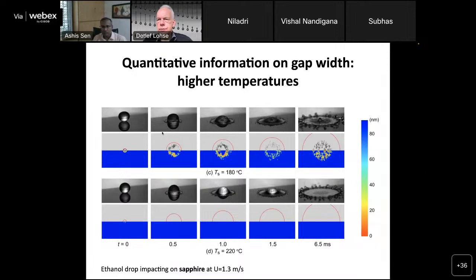More questions? Yeah, Detlef, Cam here. I was a little bit surprised. We also published that the substrate and its thermal conductivity is more or less determining the Leidenfrost point. And we use the effusivity. You didn't mention the effusivity. You talked about the thermal conductivity and the thermal capacity, but isn't the effusivity actually the parameter you want to use to say how fast the substrate can deliver the heat into the vapor layer?